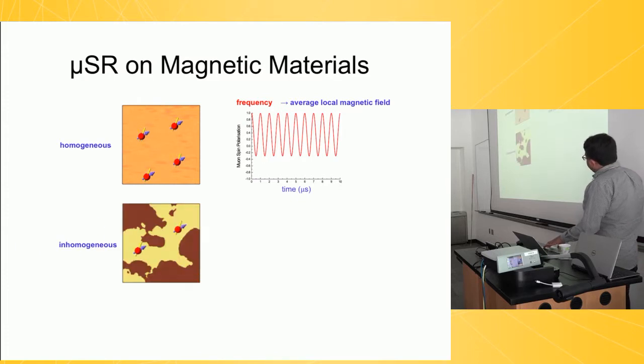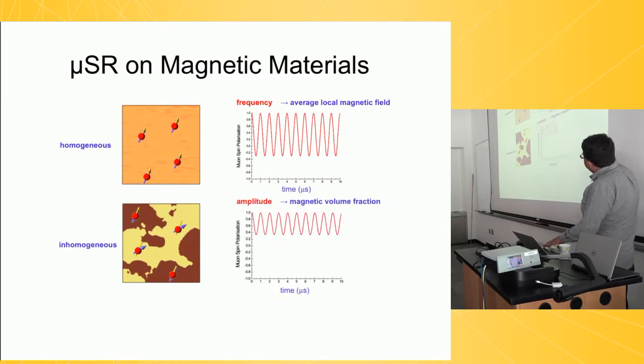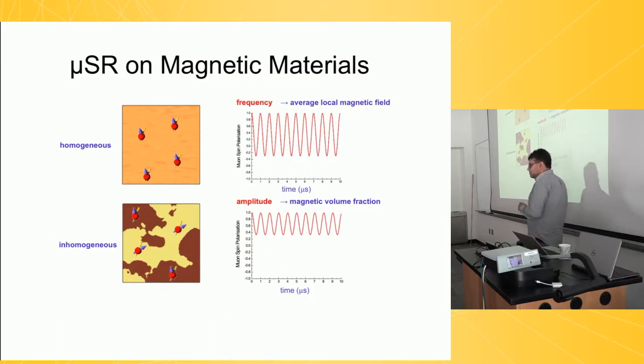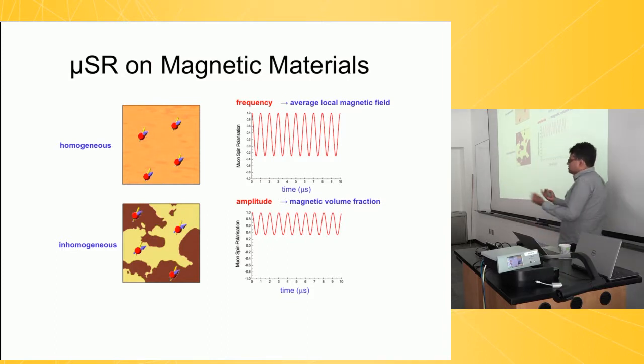On the other hand, if I have a sample that's inhomogeneous, so here's my inhomogeneous sample, these muons are precessing, maybe other muons do not precess, and then what you expect to see is a smaller component. So by counting how many muons I see in my asymmetry, I can say what fraction of my sample is magnetic.